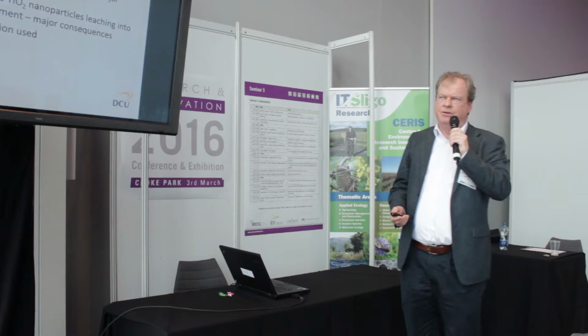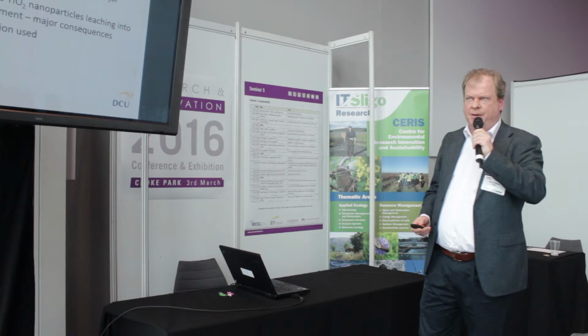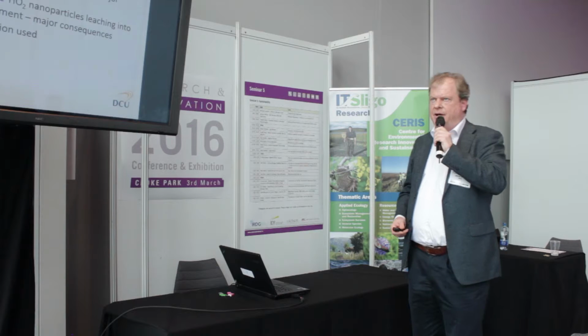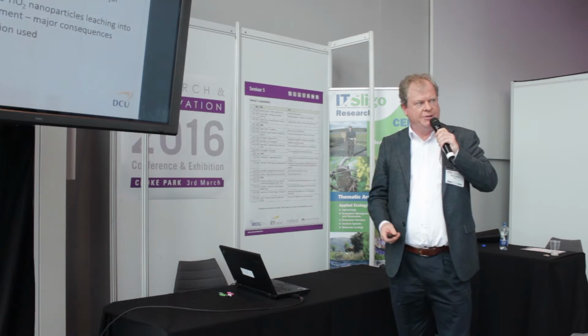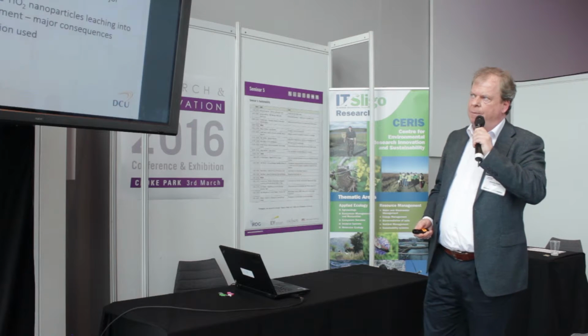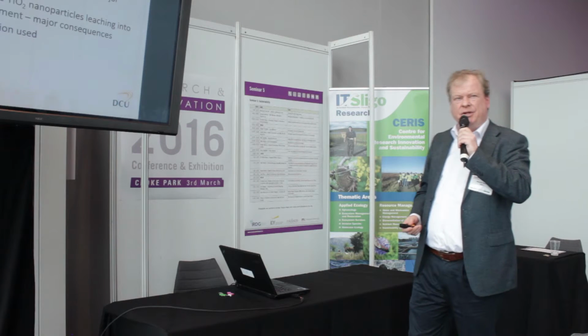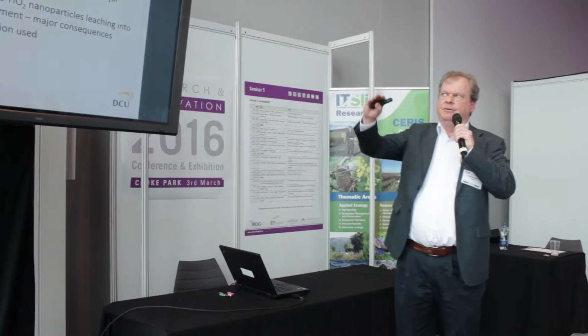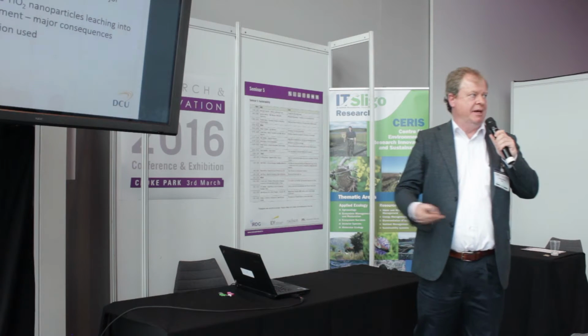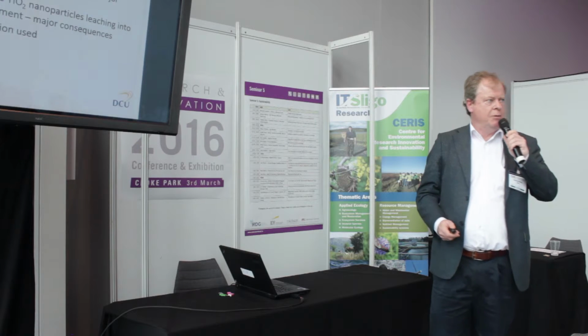Now there are problems with TiO2, and that is TiO2 usually comes as nanoparticles. You want to optimize your surface area to optimize the amount of hydroxyl radical you generate. So the removal of the particles themselves from a water body is actually a problem in what you're treating. You can't have TiO2 obviously leaching into the environment, and of course the UV region also is used. Just to mention, we have screened TiO2 here in Ireland in the summertime, and it does work with Irish solar light, okay? But it's not as effective.